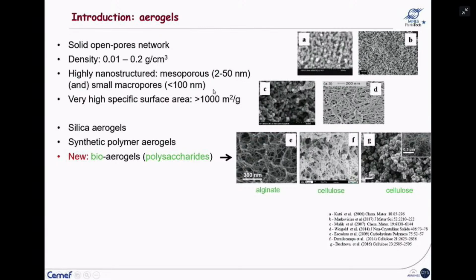And due to this nanostructuration, very low density and high porosity, these materials have very high specific surface area. The specific surface area is the sum of the areas of all internal pores. It can go up to and even above 1,000 square meters per gram. This is huge.